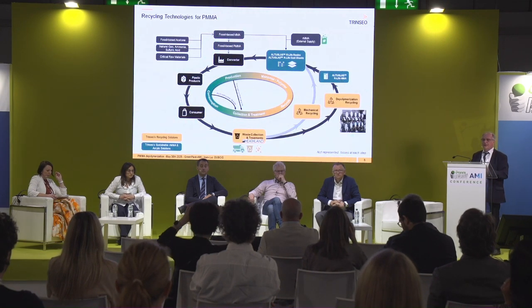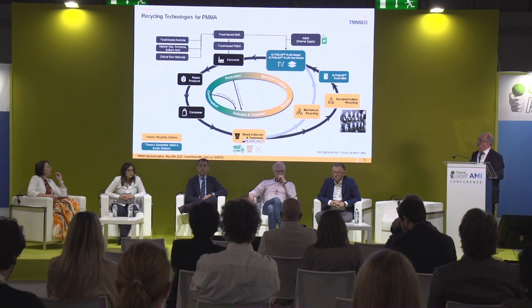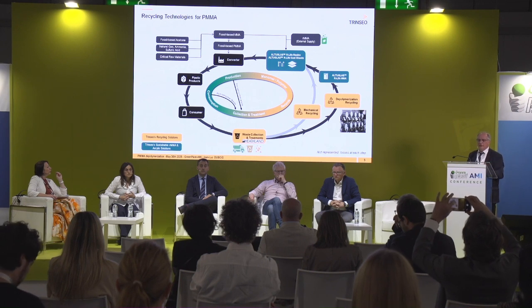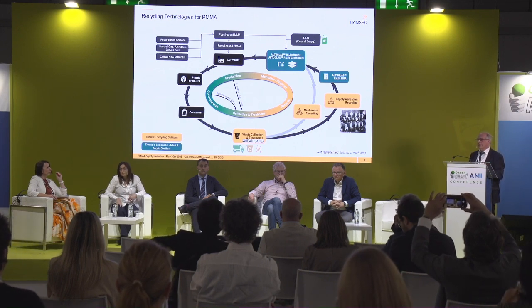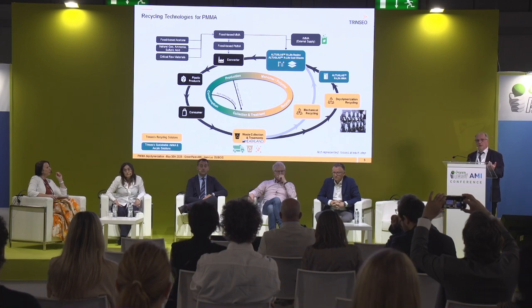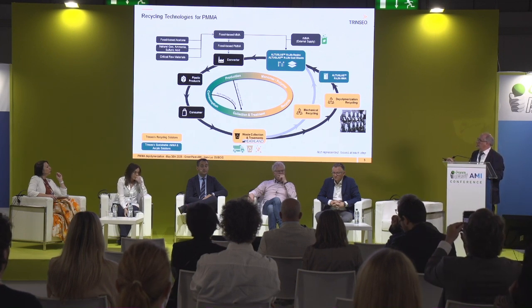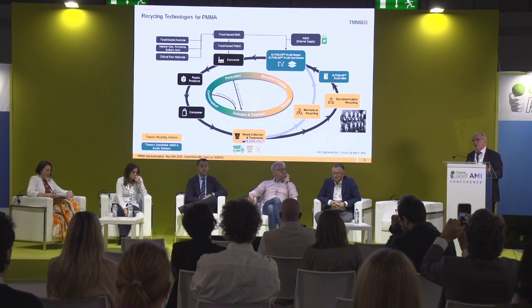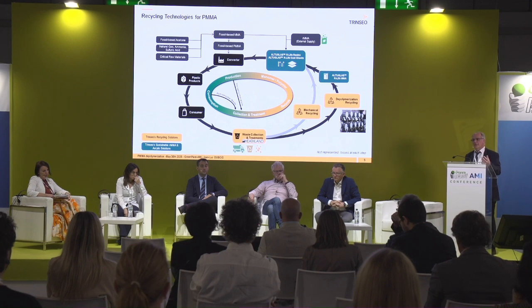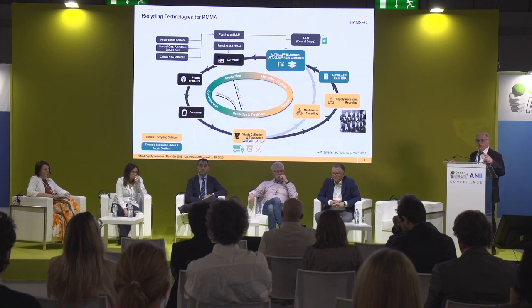Okay, back to PMMA. Especially in Europe, to make the virgin monomer and virgin polymer, we use a technology based on acetone. Acetone is a raw material, but we also need natural gas, ammonia. We also need sulfuric acid. We produce the monomer, but also ammonium sulfate in the process. And what is also important, we need a lot of what we call critical raw materials. For example, we need platinum in one of the catalytic steps, and we need graphite for one of the process equipment, and so on.